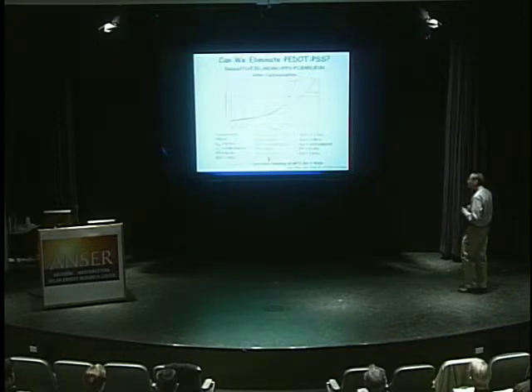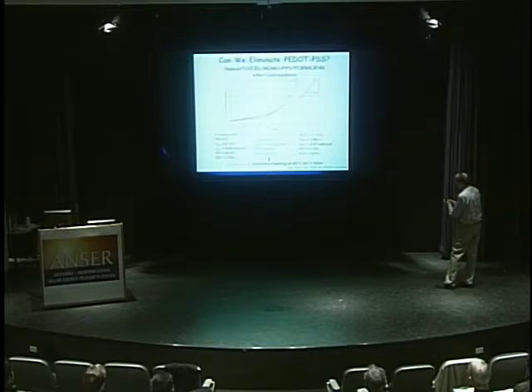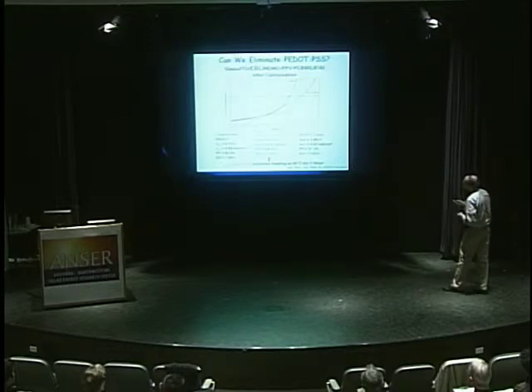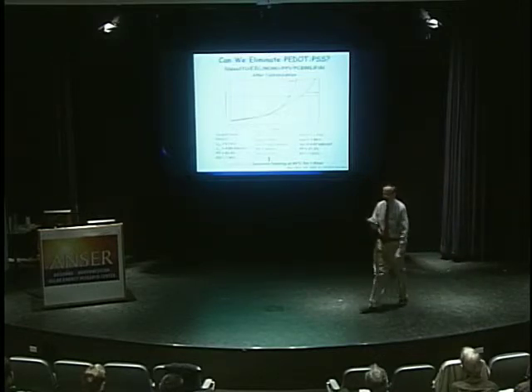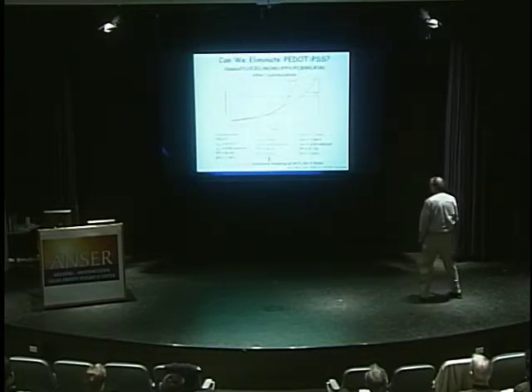And I'll come back and say one other thing. Now you might say, well, to really do a proper control, you should use both PEDOT and this electron blocking layer. We do that, and it's interesting. You get a very high open circuit voltage, but the reason is you've essentially put in a Schottky diode. Look at the slope here. So you've got a lot of series resistance, and the current has not improved any. Then what Alex did is he took all 3 cells and put them on a hot plate for 1 hour at 60 degrees C. And only one of the cells actually survived. The others degraded quite remarkably.